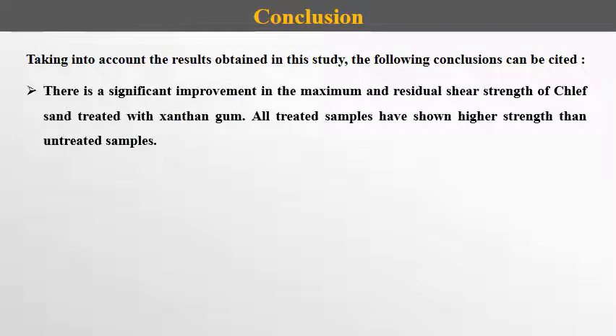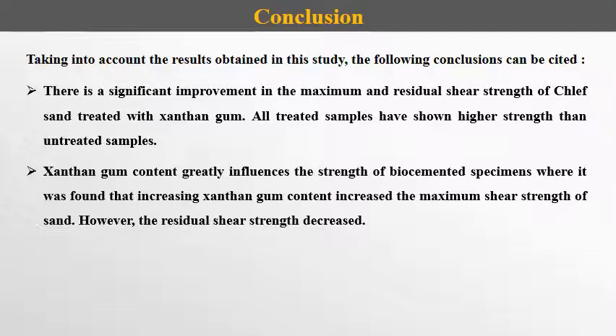As a conclusion, taking into account the results obtained in the study, the following conclusions can be cited. There is a significant improvement in the maximum and residual shear strength of Chlef sands treated with xanthan gum. All treated samples have shown higher strength than untreated samples. Xanthan gum content greatly influences the strength of biocemented specimens, where it was found that increasing xanthan gum content increased the maximum shear strength of sand. However, the residual shear strength decreased.